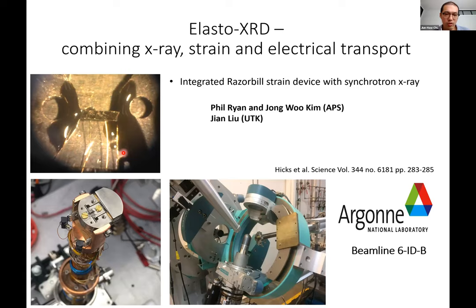So now all this past result motivates us to further look into this process of strain detuning, or straining, the iron-based superconductor. Working with Phil Ryan, Jong-Woo Kim, and Jian Liu, we have developed this sample environment where we mount the Razorbill strain cells on the X-ray diffractometers. And